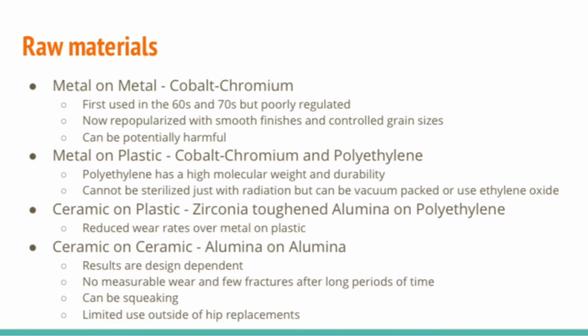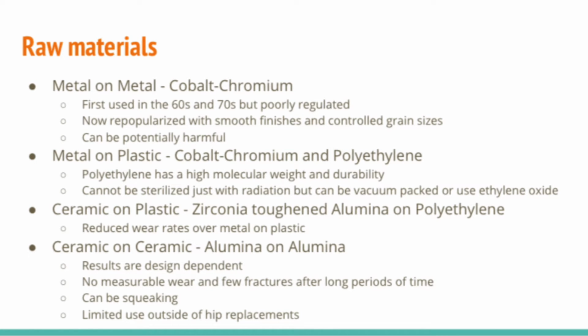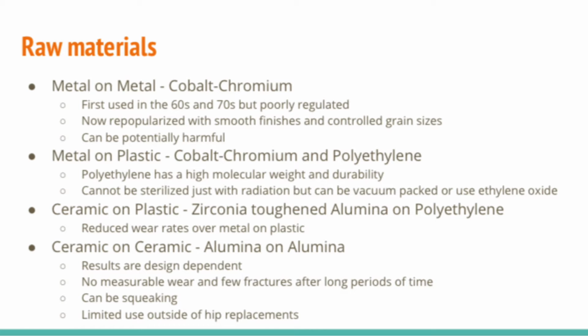Metal on metal can also lead to toxicity poisoning, which is what led to the idea of replacing part of it with plastic. Metal on plastic is made from the same metals and polyethylene. Polyethylene is useful due to its high molecular weight and durability. It cannot be sterilized with gamma radiation while exposed in the air because the radiation breaks the chains and the broken ends will react with the oxygen present. This will decrease the molecular weight, ductility, and the strength of the polyethylene. This also leads to more wear, which means needing a new joint sooner.